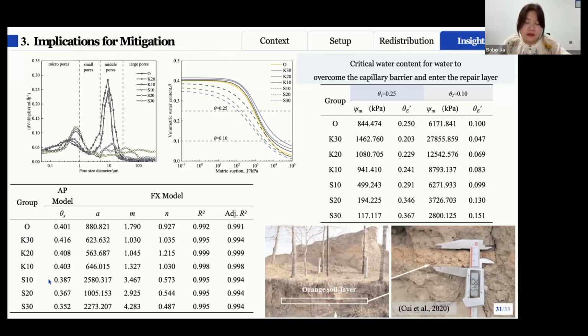We can also get an example from reality, because the field observation reported by Cui showed that a specific soil layer exists at the base of the Great Wall in Qinghai province. This layer lacks effective capillary pore structures and therefore does not provide pathways for salt migration from the foundation to the wall. As a result, this section of the wall has not developed significant salt damage over several centuries of exposure.